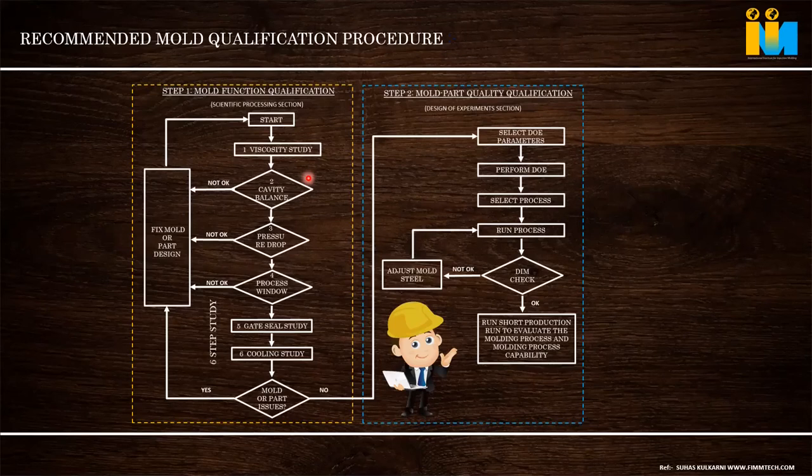Exactly. And the conduction of the steel also changes it. If you are using stainless steel, it is different. Your H13 is different. If you are using beryllium copper, it is totally different. So that also matters. Conduction, convection, radiation from the mold. If the mold plate size is bigger, cooling time will automatically reduce because it pulls away the heat very quickly. The cooling lines are better. So finally, cooling time varies based on how the mold is made, not only the raw material. So it is a study.